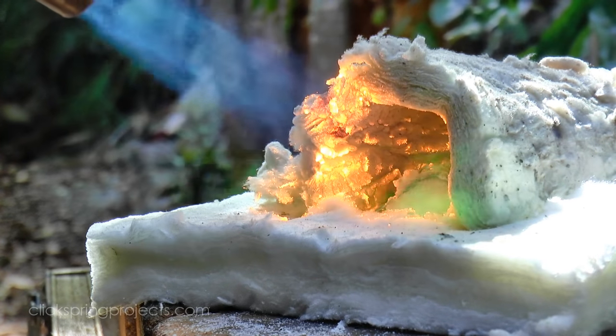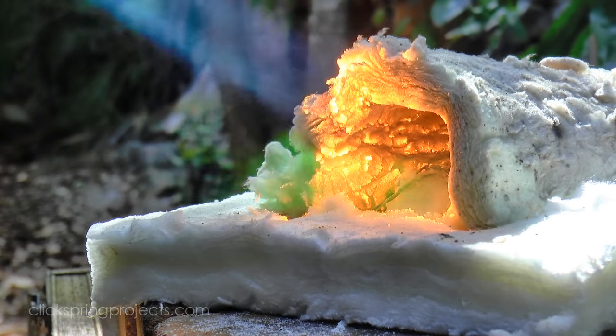And now that most of the shaping of the cutter is complete, it can be taken to a red heat, quenched in oil to harden, and then slowly tempered to a light straw color.